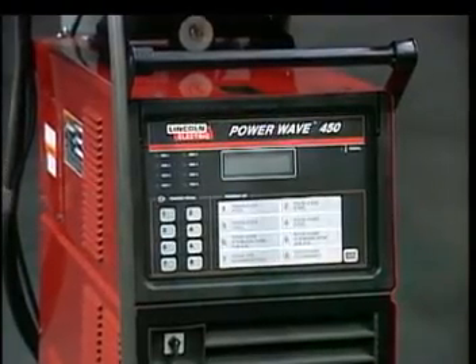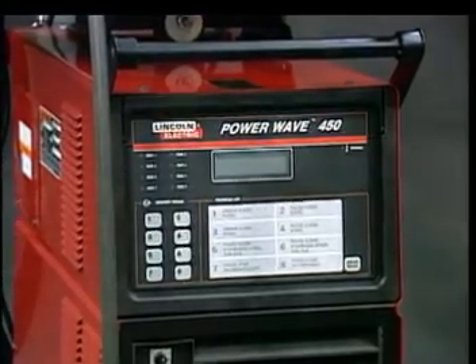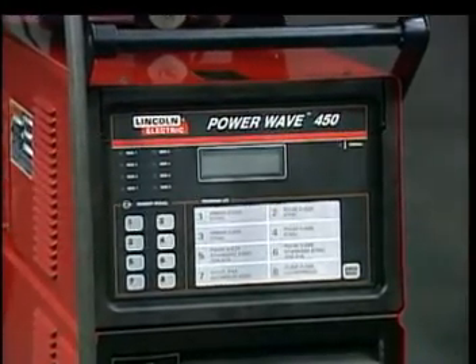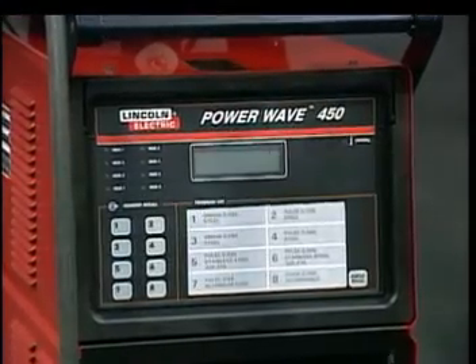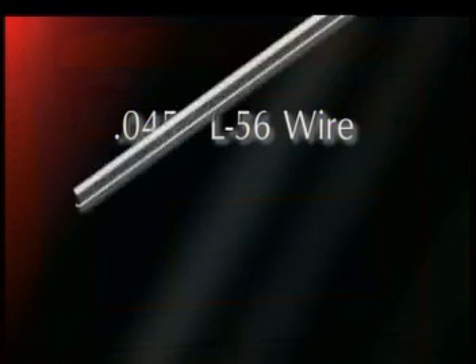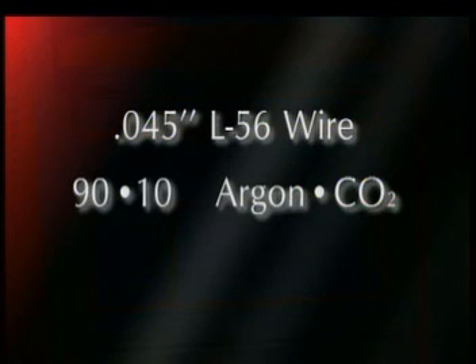Controlling the welding process depends on how we change the instantaneous parameters together to achieve the most stable arc. The magic of the Power Wave is that we have pre-programmed a computer to help you set welding procedures. We took a Power Wave synergic power source and loaded it with .045 L56 wire and used a 90/10 argon CO2 blend. We started at 100 inches per minute wire feed speed and increased the procedure to 650 inches per minute. The synergic property of the Power Wave sets the correct arc length for each wire feed speed.